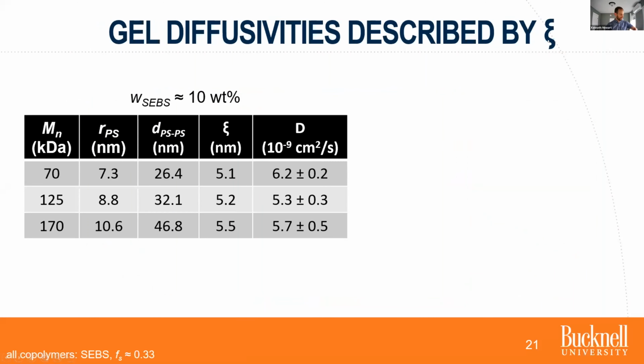The final kind of test we did to explore this further was to use a few different triblock copolymers varying in molecular weight. These all have approximately the same fraction of polystyrene at 33%. But because of their different molecular weights, they have different polystyrene radii, as shown here. They have considerably different spacing between the polystyrene domains, from 26 for the lowest molecular weight up to 46 for the highest molecular weight, but their mesh size is approximately the same. And so this gives us a tailoring of one parameter in pretty vast change, while fixing the other one. These are all the same polymer concentration. This is 10 weight % in the swollen state.